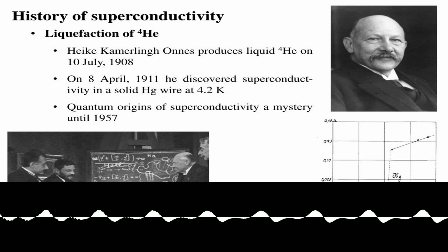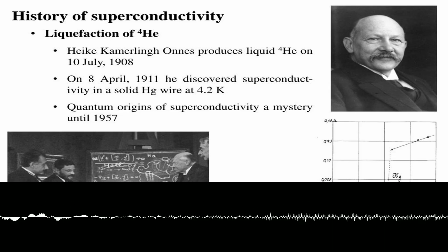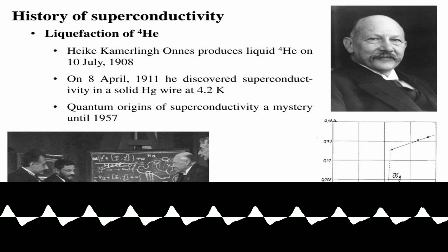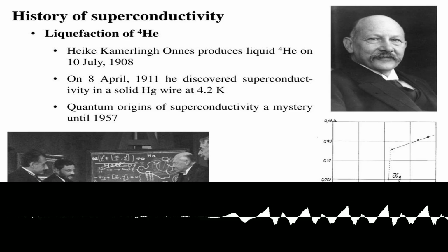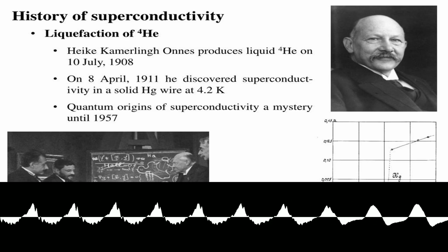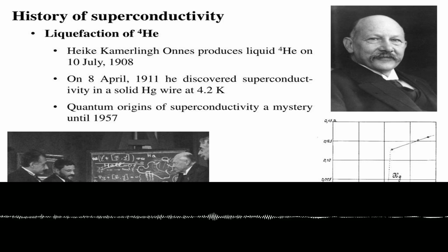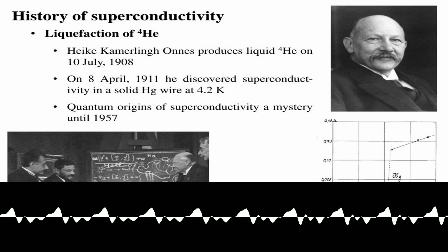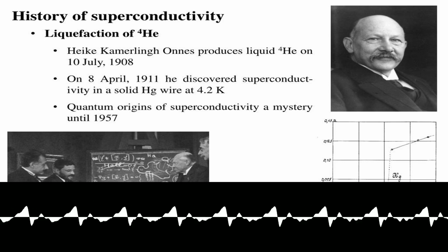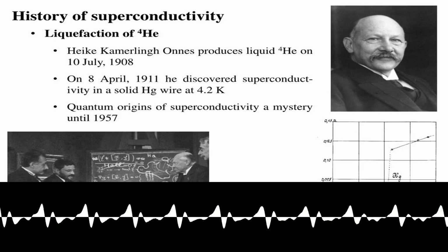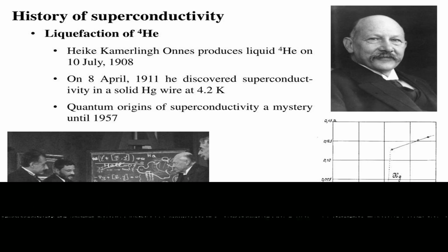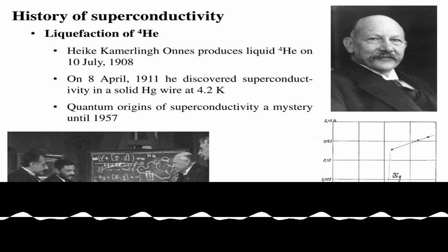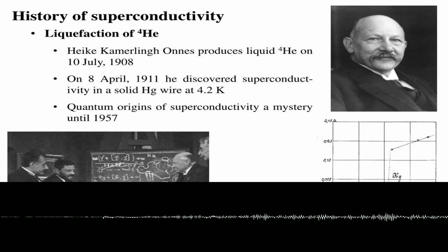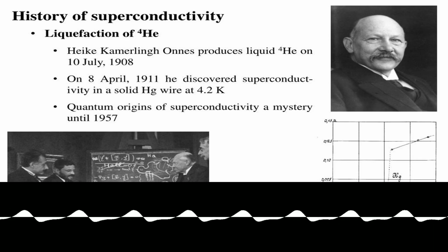Their evaluation of the residual resistance was a masterpiece of careful measurement. Using a sensitive galvanometer, they established an upper limit on any remaining resistance, an upper bound that was many orders of magnitude smaller than the resistance of the purest copper at that same temperature. The power of their argument came from the stark, unambiguous nature of the data, which presented a phenomenon that defied the established theoretical models of electrical conduction in metals.